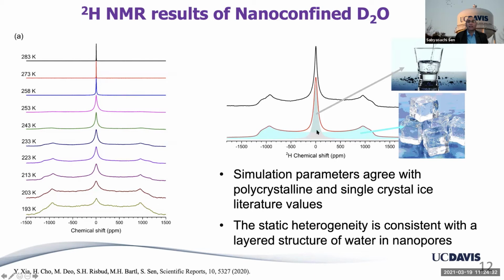So this peak at the center we know corresponds to liquid-like water, and this peak gets narrower and narrower, and eventually this entire broad component decreases and everything gets very, very narrow. So this is the behavior if you put a drop of water inside a magnet and you collect an NMR spectrum that will look like this. The line shape is so narrow. It's a typical liquid-like NMR line shape, which says that all the water molecules are moving extremely fast. They're rotating, tumbling, diffusing, whatnot.